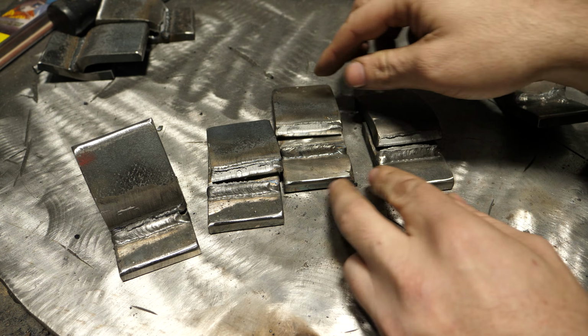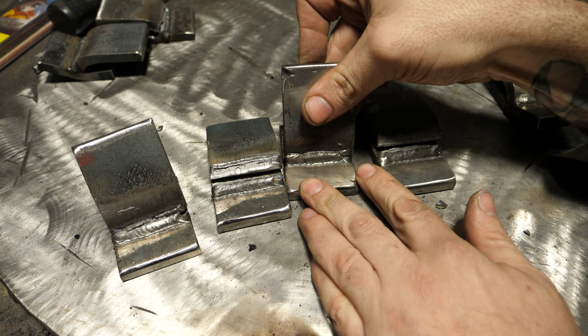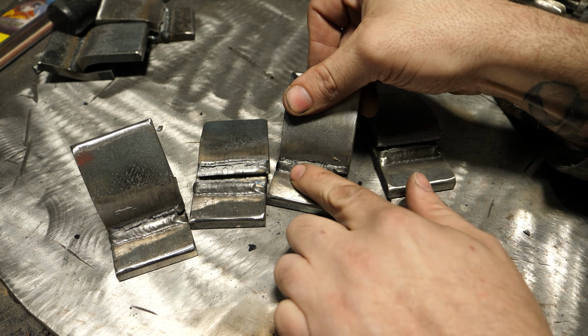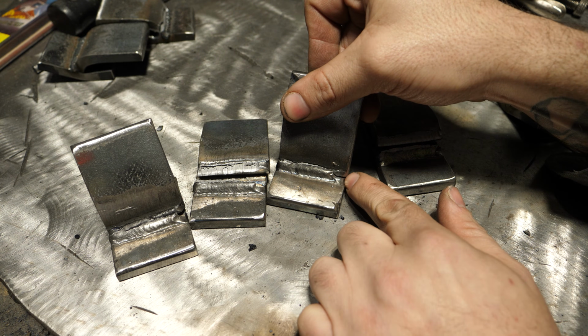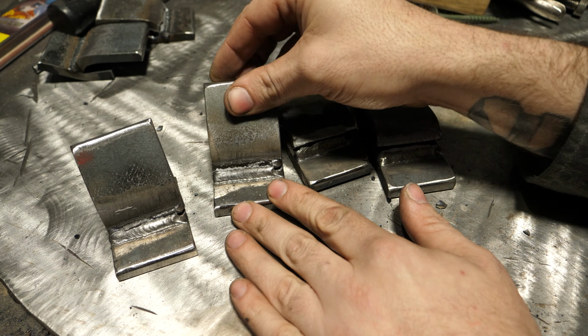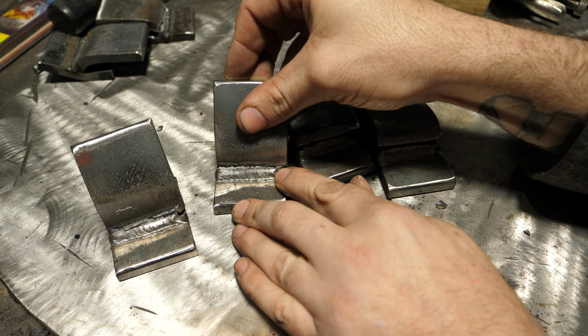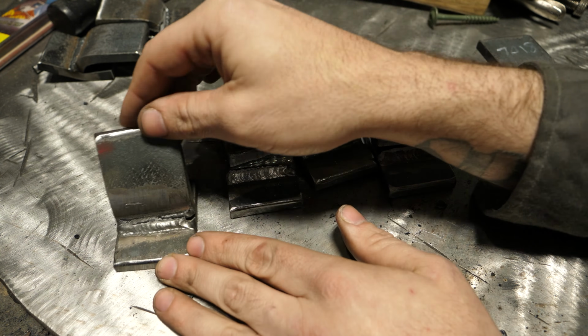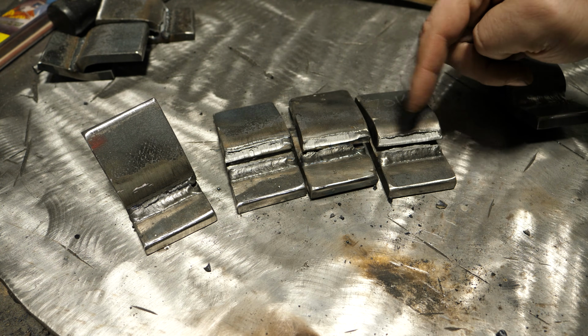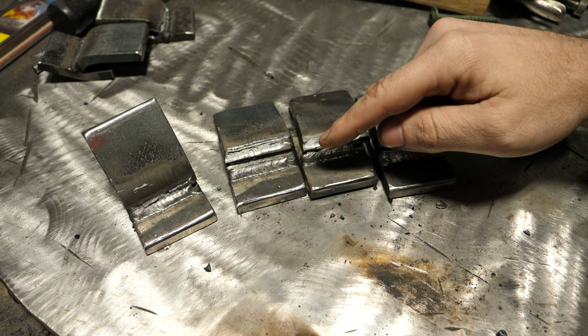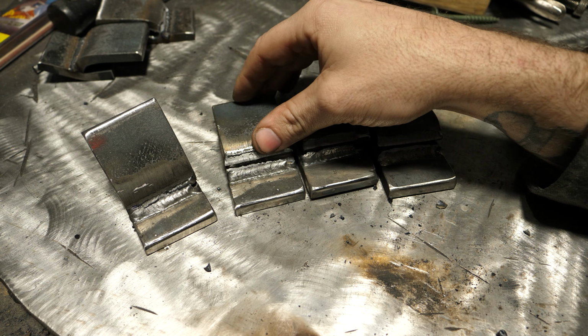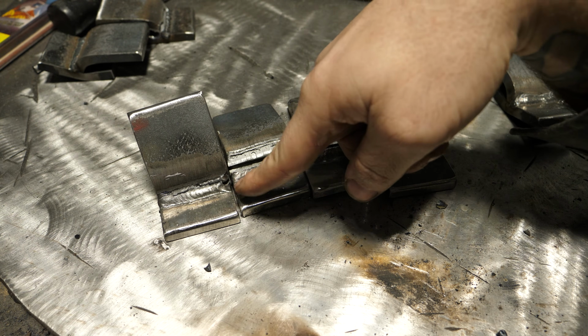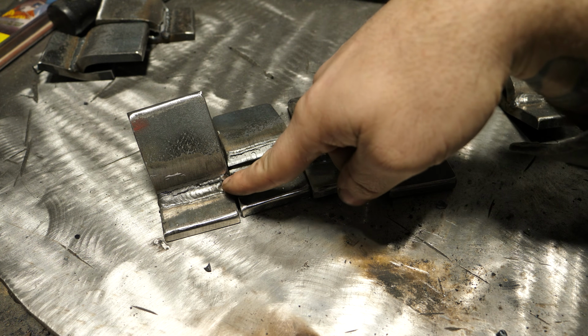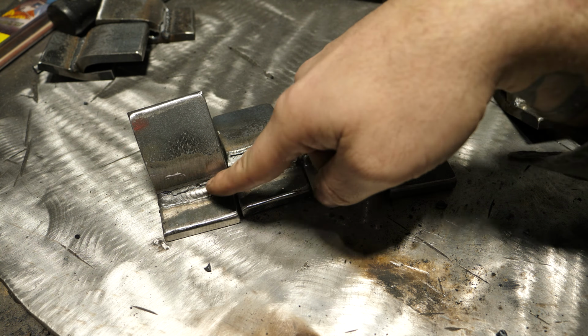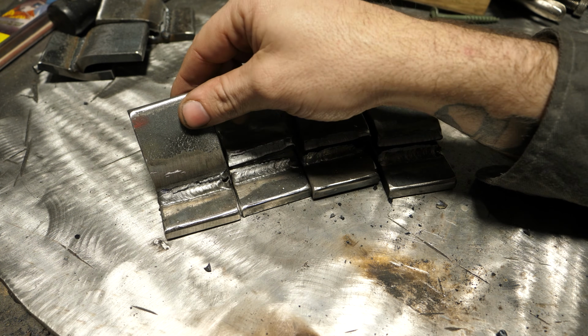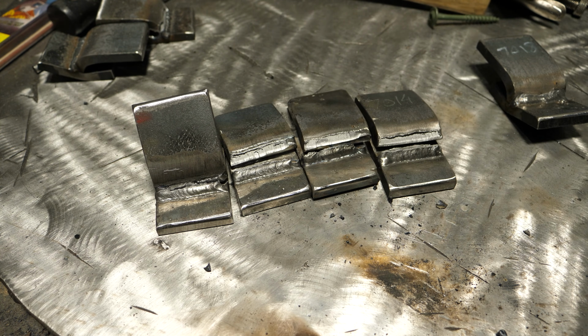That one broke real close to the edge. This one broke a little bit closer, this way from the end, which again, that's the thinnest part of the weld. Same thing here. As soon as the weld got thick enough, boom, and then it tore off the weld. So I would say the consistency here is that the weld itself is going to break off of the plate. This one is still somewhat attached, but again, you can see the weakest point of the weld when stressed is there, and as soon as this weld got enough tension against it, it just tore the weld off the plate basically.